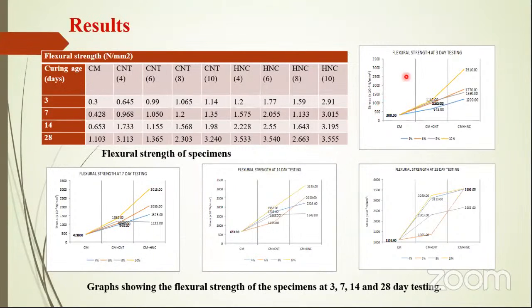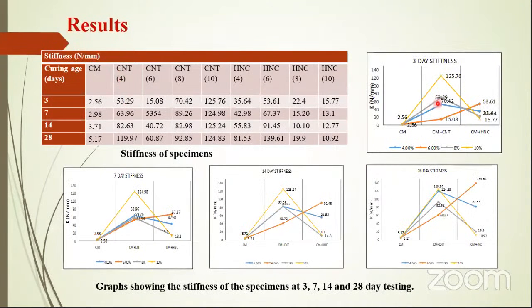Whereas in case of CNTs, the strength gain is low. At 3 days, it is still less than HNC, and at 7 days also, it is still less than HNC, even on 14-day. But on 28-day, you see some percentages of HNC are almost as high as CNT here. So the strength gain using HNC compounds is fast and higher, whereas in case of CNT, it is higher, but it is slower.